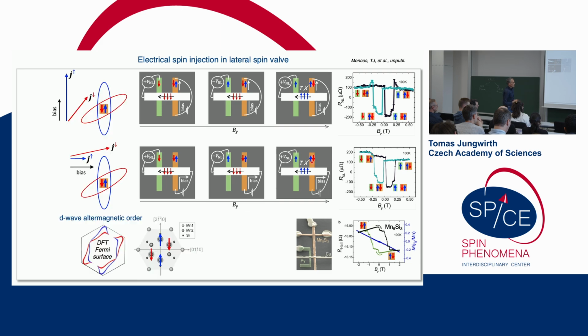But with the picture of the altermagnetic order, you can understand it very straightforwardly, because, as we explained, now here's the answer to who was asking about hexagonal. This is the lattice. It's hexagonal. In the non-magnetic phase, you have these 6 equivalent manganese atoms, but in the ordered phase, and that's known from neutrons, only 4 of them are magnetically ordered. So they form this D-wave type of altermagnetic order.